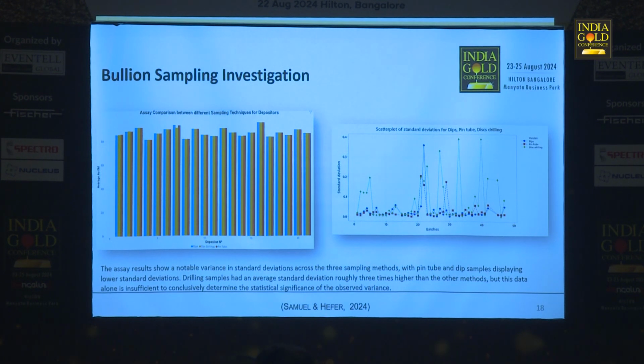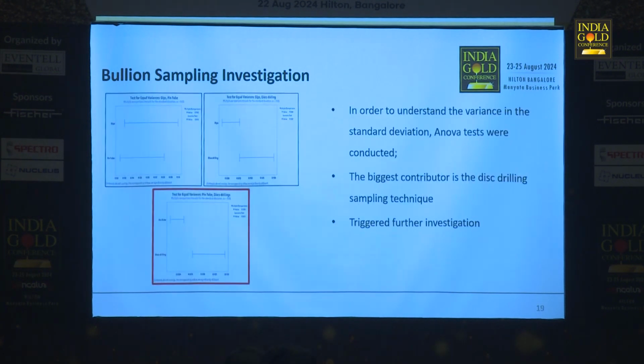So what we did is use the F test to understand, and we started to compare the equal variances. Between dips and the pin tube, we didn't see much difference. Between dips and the drillings, there was a slight difference, but not much. But a big variance was seen between pin tube and the drillings. Following this, we wanted to investigate further what the cause of this is, given the purity.